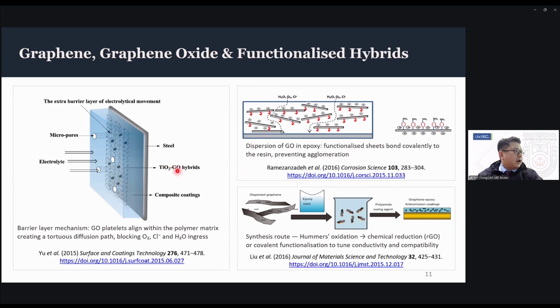They developed titanium oxide graphene oxide hybrids, and what they saw was that these additives improve the mechanical performance as well as the corrosion resistance.